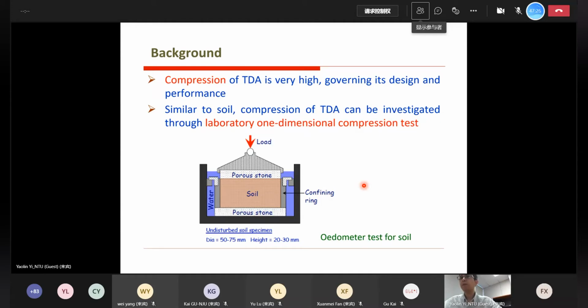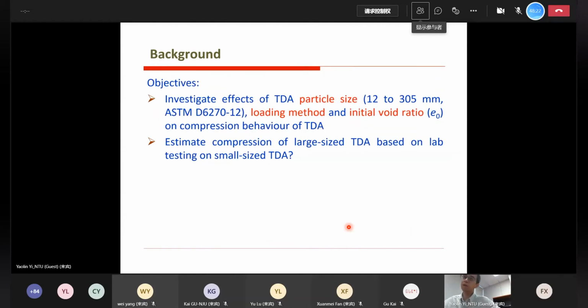But the problem is that the particle size for this material is much larger compared to soil. For soil, in geotechnical engineering, we use a very small odometer test. As shown here, the diameter is just 50 millimeters and the height just 20 to 30 millimeters. So it's very small. I think everyone is familiar with this. But for TDA, it should be very large, because the particle size can be up to 300 millimeters. So we need a very big compression model. The previous results indicated that the size affects a lot. So if you want to do the compression test, you need a very big compression model. Also, the loading method is different.